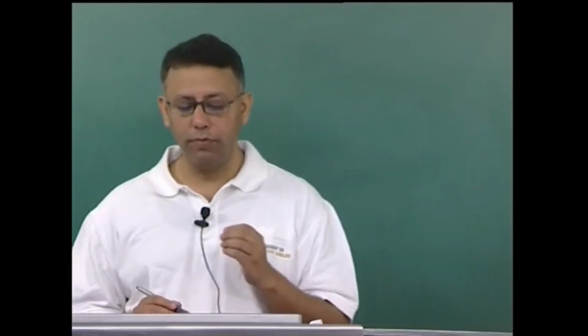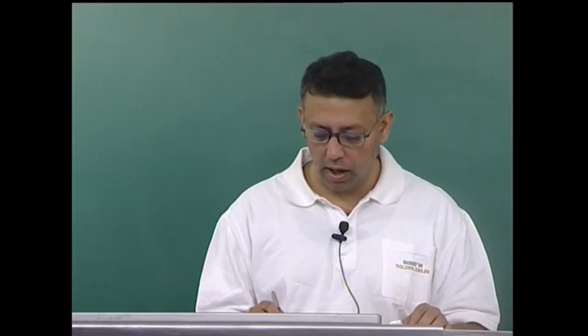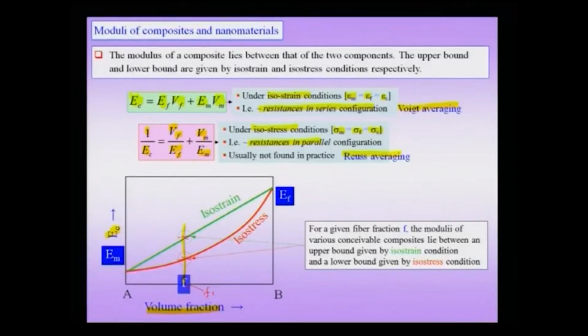The reason that the real composite is not exactly one of the two is that the matrix fiber interface could partially be slipping, could actually not be contiguous in places. Therefore, not knowing fully what the fiber is in each one of those, and their orientations and the characteristics of the interface, I can only tell that the overall average has to be between the upper bound given by the isostrain condition and the lower bound found with the isostress condition.